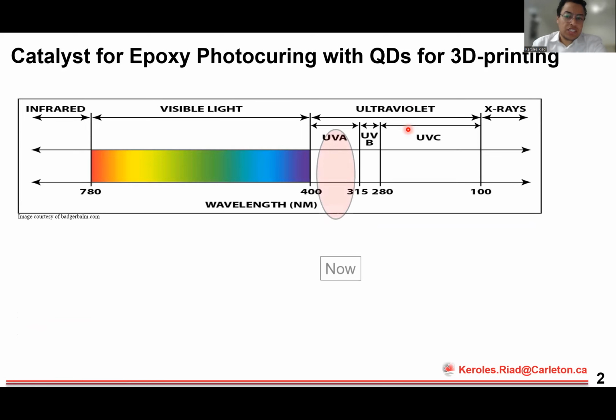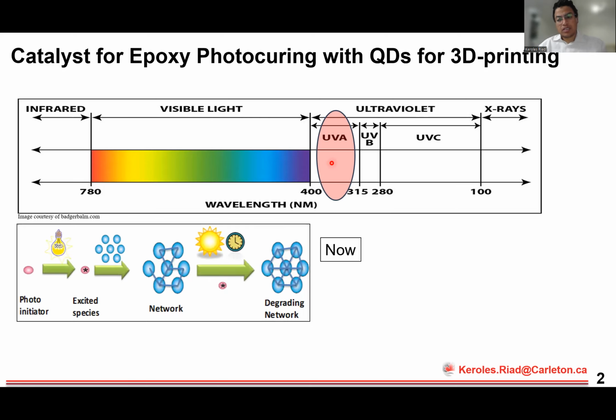Now, the challenge is that all initiators currently available have some sensitivity to the UVA region of light, which exists both in the 3D printing laser and also in the sunlight, which is why you put sunscreen at the beach. And what that means is that when you 3D print a part with stereolithography and leave it outside for a couple of weeks, the initiators that are still inside the 3D printed part absorb UV from sunlight and get excited and continue to polymerize the material.